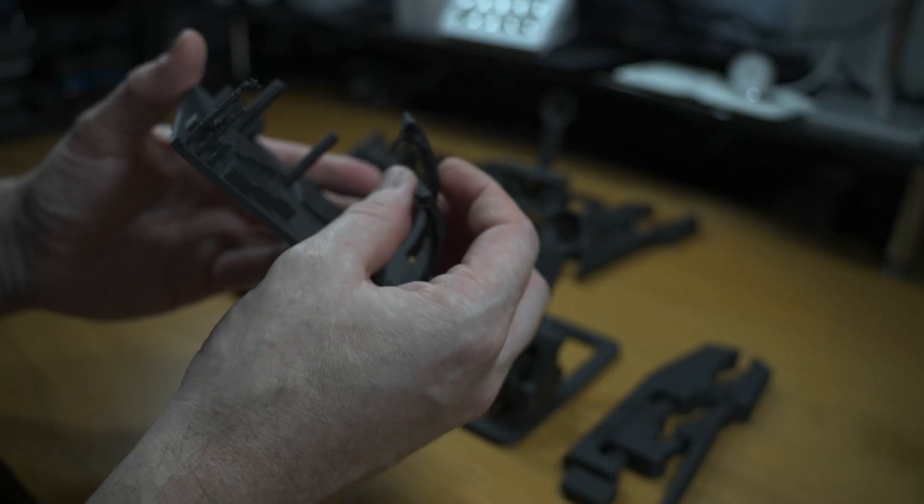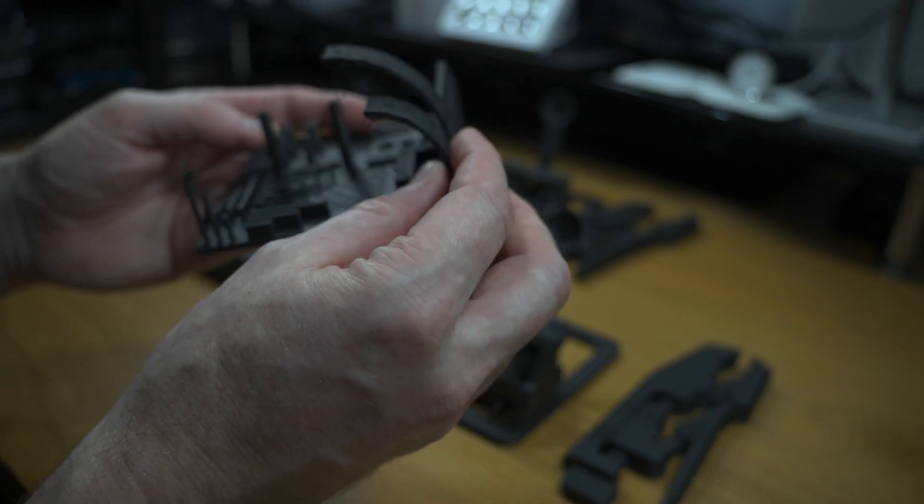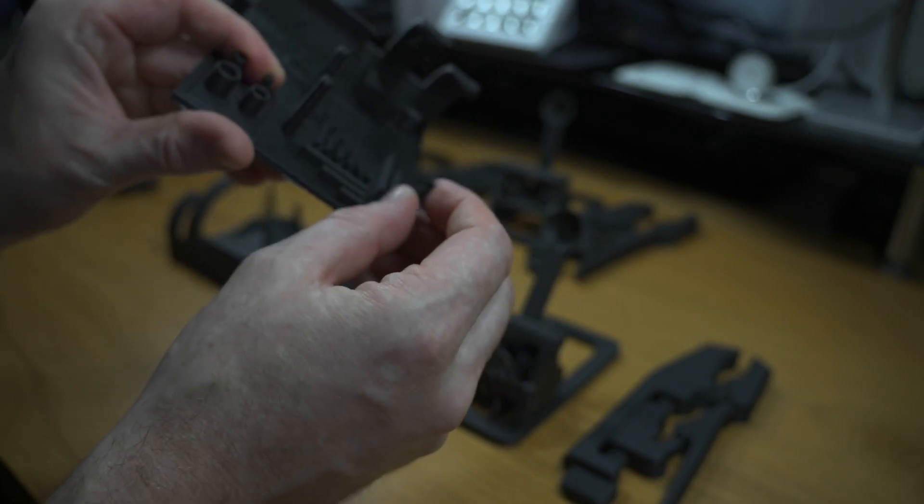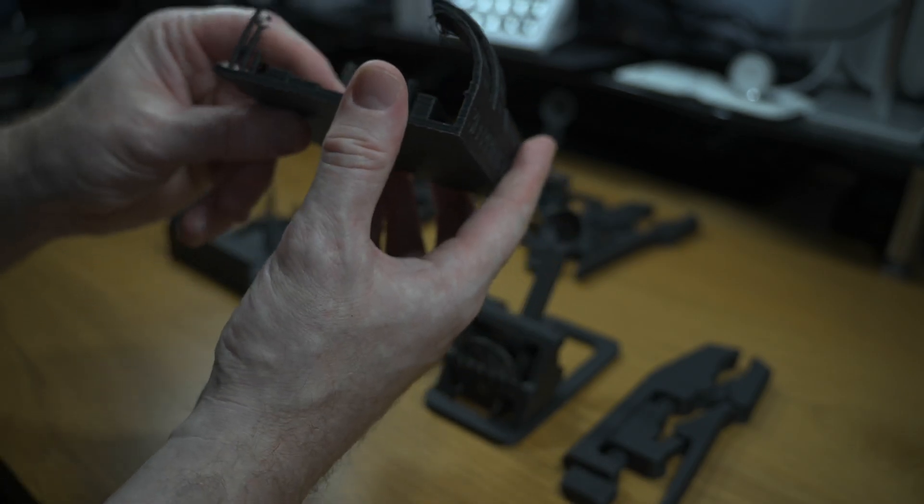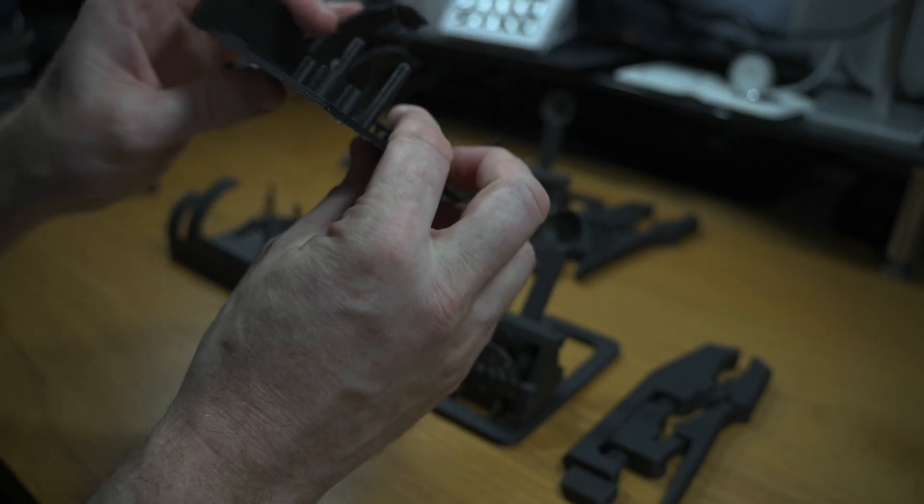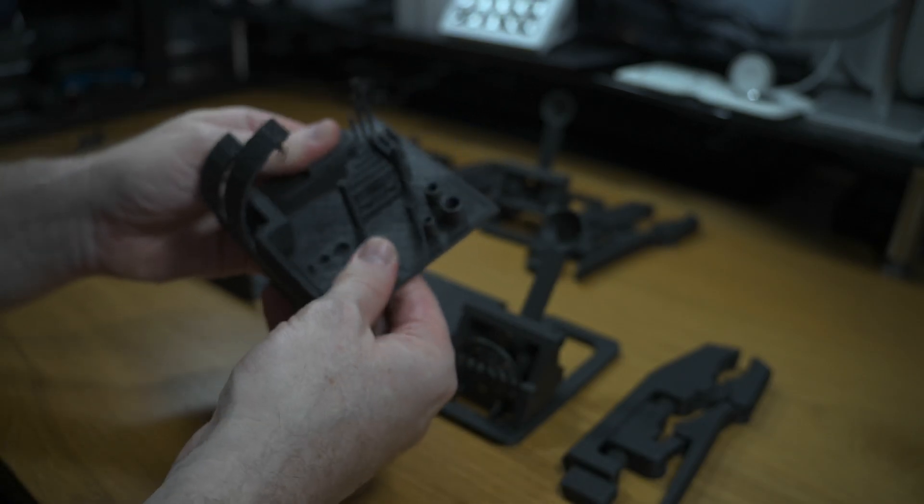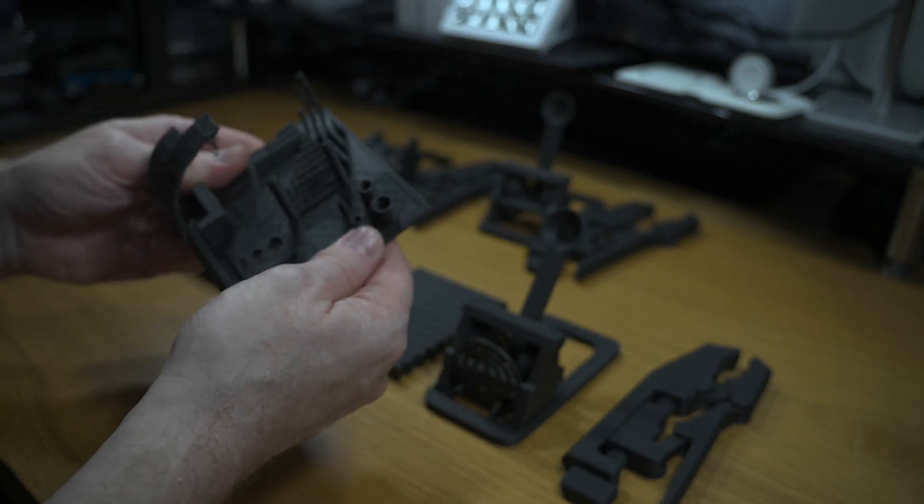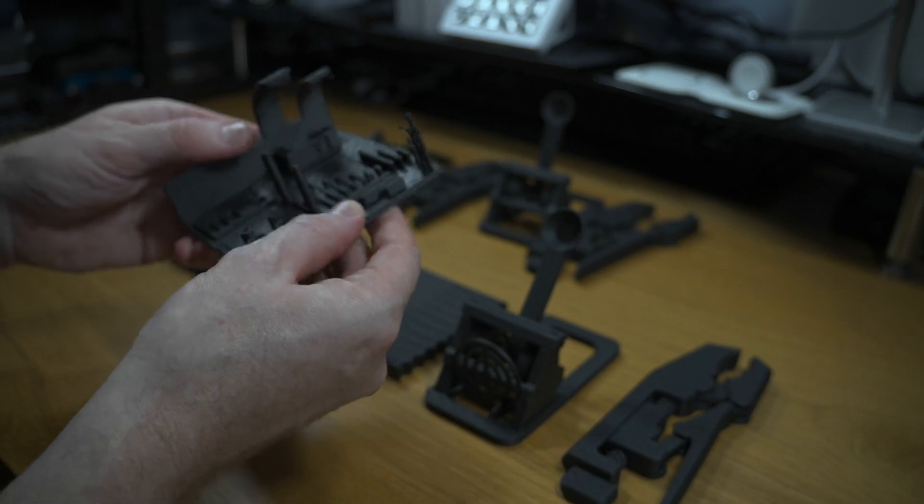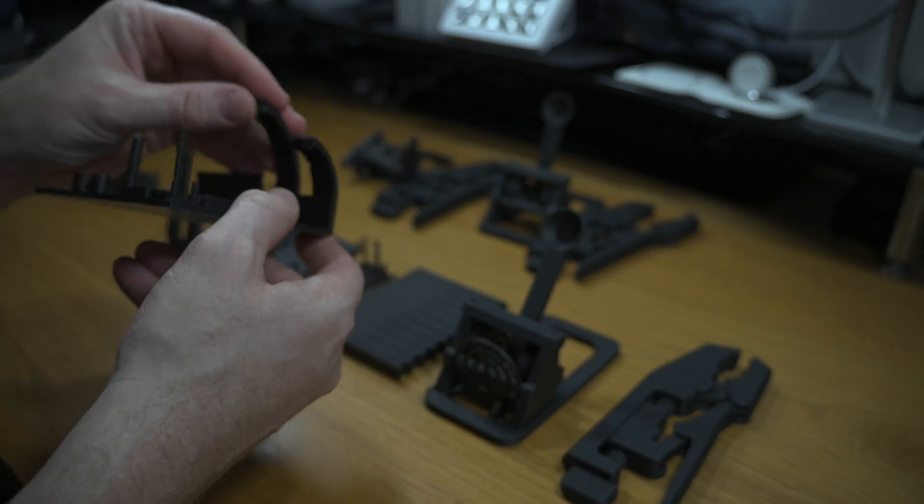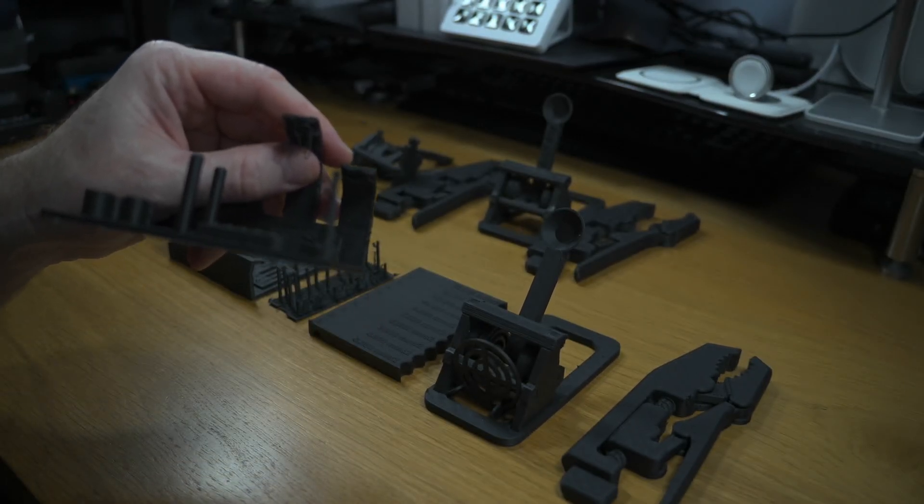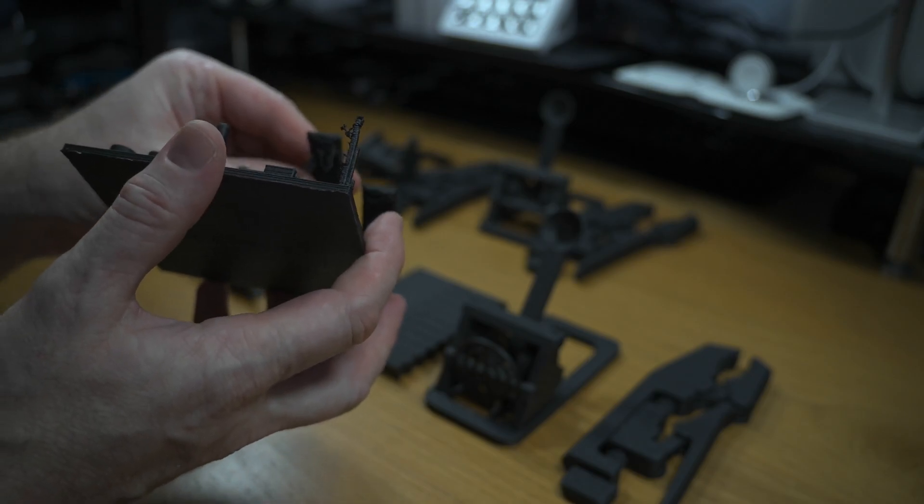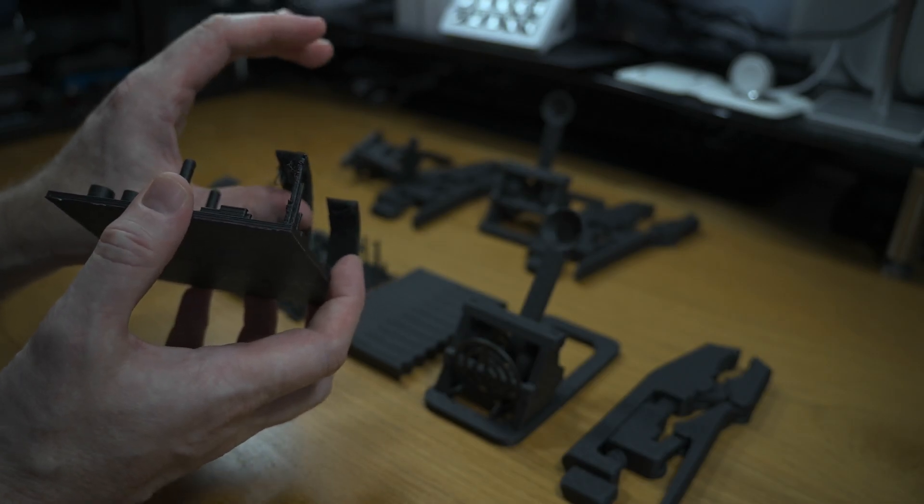This is one of the first prints I did with it and it came out pretty good. Overall overhangs and everything were reasonably good, although it did sag quite a bit here at the 80 degree angle and the 75 degree angle. There is some stringing here, but bridging pretty good. Overall strength of the piece, it's a lot stronger and stiffer than the previous prints with eight hours drying. So we're on to something here, definitely getting a better quality print. But this overhanging indicates we're probably not cooling this properly or we're printing so fast that it's not getting a chance to cool properly.